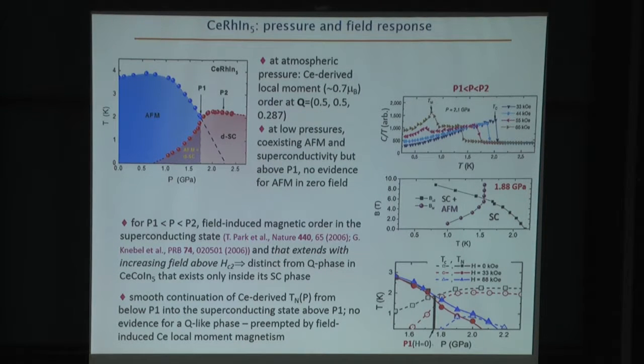So now let's come to cerium rhodium indium-5 (CeRhIn5), which I said orders antiferromagnetically at atmospheric pressure. This antiferromagnetic order is derived from the 4f electrons of cerium. The ordered moment is very large in contrast to the spin density wave order that we've been discussing. It's much, much larger, and this ordering appears at a very different Q vector. So if we apply pressure to cerium rhodium indium-5 (CeRhIn5), this Néel order initially increases and then begins to decrease. And there are a range of pressures below this pressure we call P1, where antiferromagnetic order and superconductivity coexist.